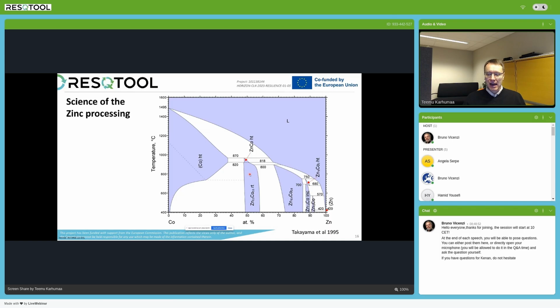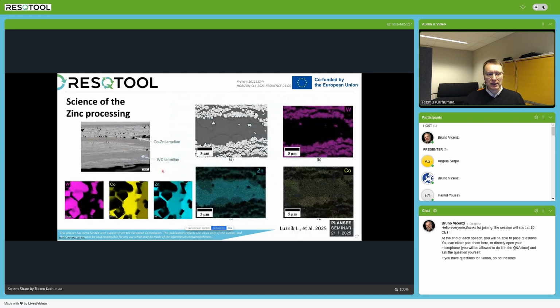We can also have phases in the structure which have higher amount of zinc, and on the other hand, we know that there is also dissolution of the cobalt from the hard metal parts into the molten zinc. So then in this case, we start moving from this part of the diagram towards the center. So we have multiple phases at the same time existing in the reacted material. And typically the parts look like this on the left side. There is a lamella structure, and these lamellas consist of tungsten carbide rich lamellas, and then zinc-cobalt rich lamellas.